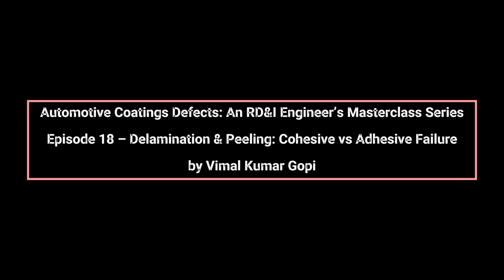The key takeaway is that delamination and peeling are system-level failures, not isolated paint defects. Appearance, gloss, and early test results cannot predict them reliably. Long-term success depends on managing surface energy, interlayer chemistry, internal stress, and environmental durability together. Once peeling begins, repair options are limited and costly. Prevention through disciplined process control and material understanding is the only sustainable solution.